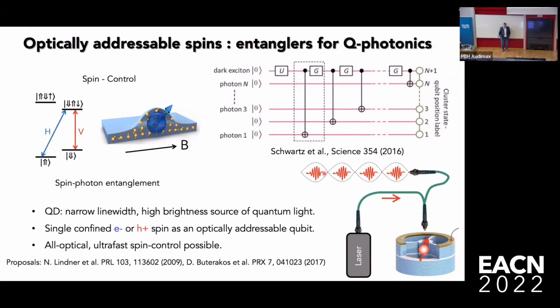And linear cluster states are not useful in the scenario of quantum repeaters, but this is for one spin, where a photon is scattered, the spin is then manipulated, another photon is then scattered to build up the size of the cluster state. What you can do is the same kind of thing with two spins, for example, in the scenario of a quantum dot molecule. So if you want to use this spin as an entangler for photons, you can build up cluster states, and the efficiency and usefulness of this depends both on the photon extraction efficiency and the coherence time compared with the control time, and these are picoseconds.